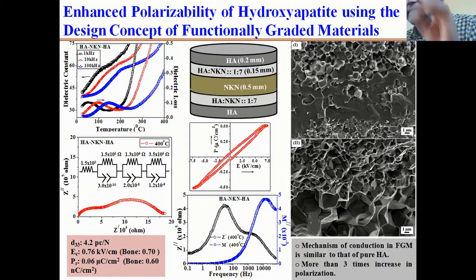This layer is just one optimized ratio of hydroxyapatite to sodium potassium niobate, just to avoid the mismatch of thermal properties, because they have to be processed at high temperature, right? And their coefficients of thermal expansion are different. So just to compensate such a mismatch in their thermal expansion coefficients, a buffer layer has been introduced. This buffer layer is an optimized layer, meaning different compositions were tried, and at the one particular composition which is mentioned here, it has been observed that the layers are very well integrated.